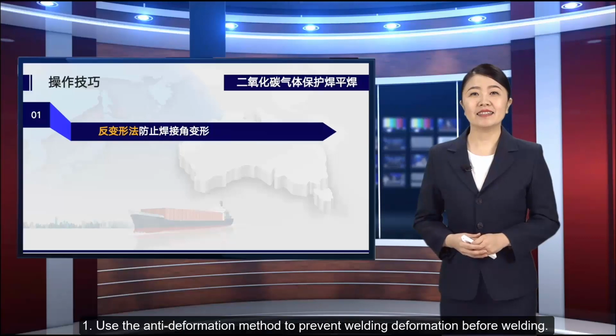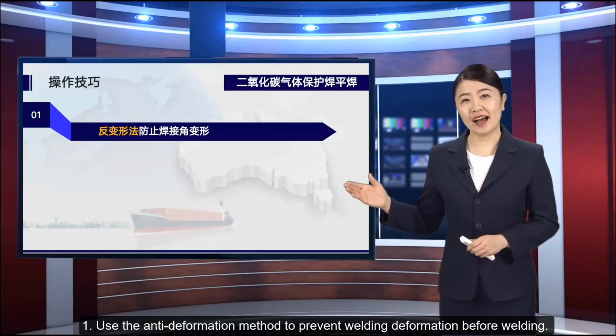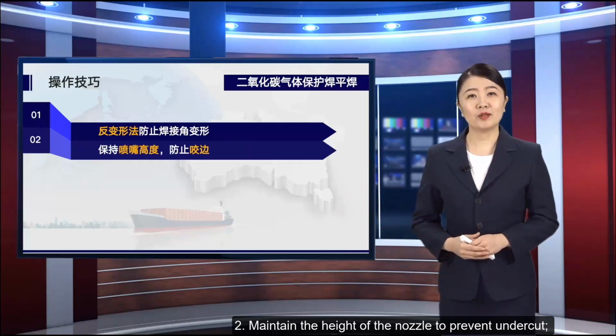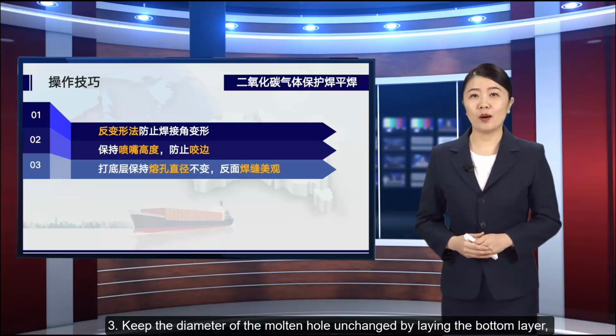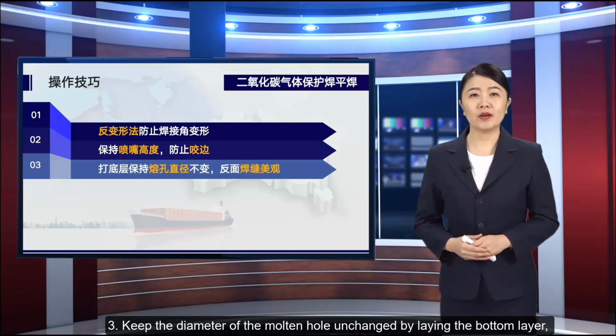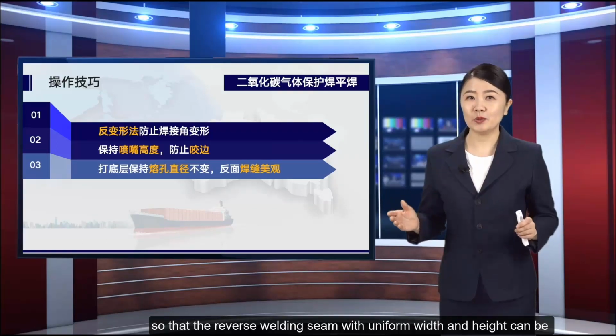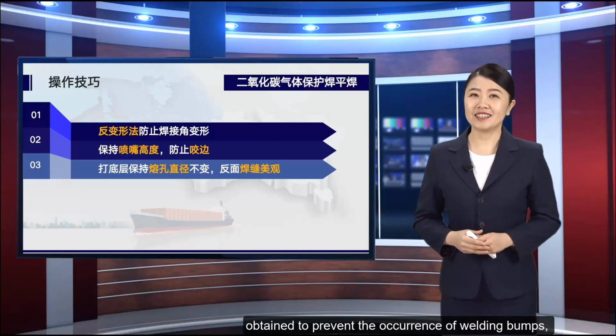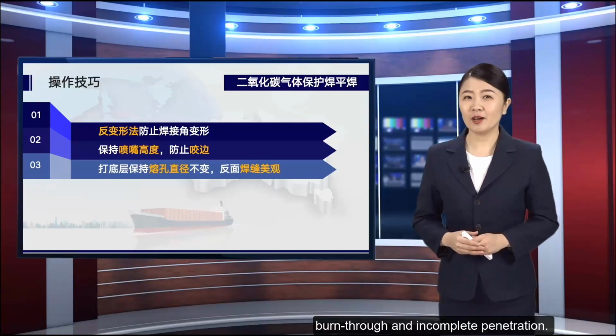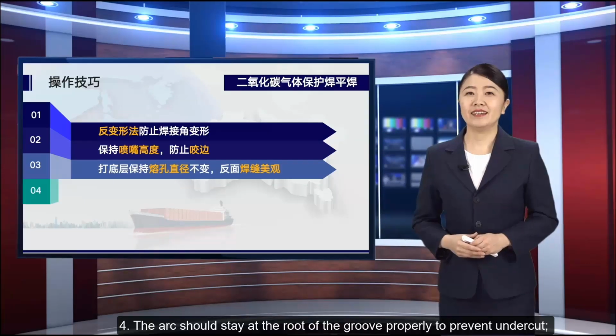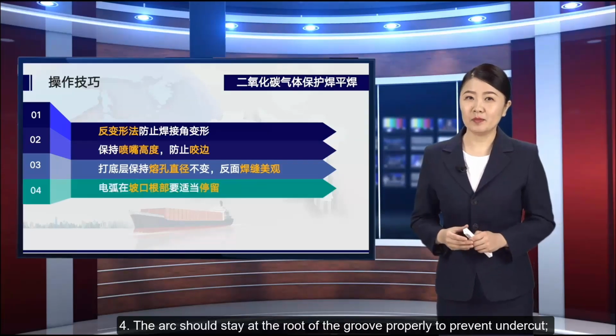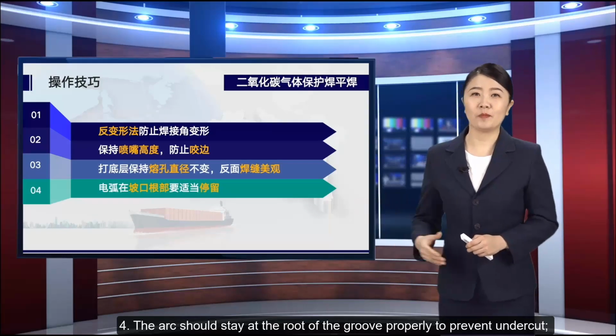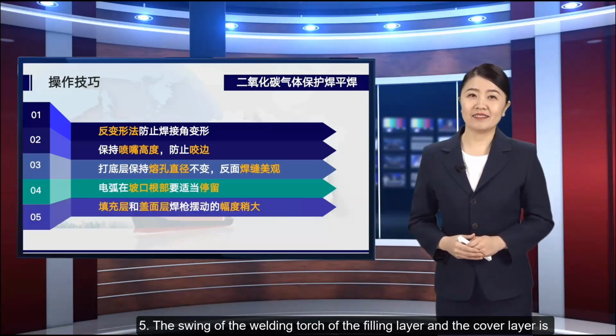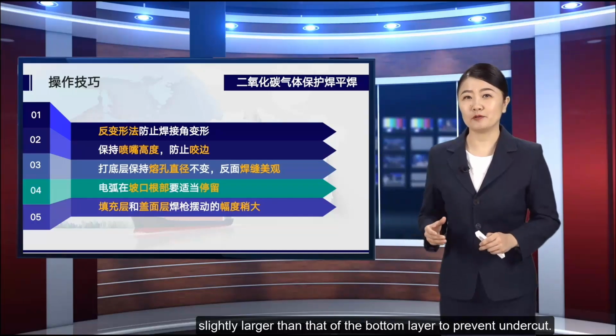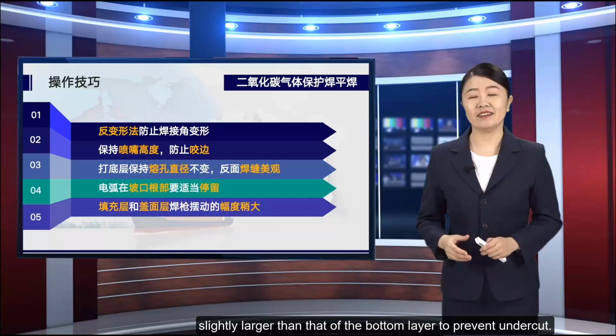1. Use the anti-deformation method to prevent welding deformation before welding. 2. Maintain the height of the nozzle to prevent undercut. 3. Keep the diameter of the molten hole unchanged by laying the bottom layer, so that the reverse welding seam with uniform width and height can be obtained to prevent the occurrence of welding bumps, burn through and incomplete penetration. 4. The arc should stay at the root of the groove properly to prevent undercut. 5. The swing of the welding torch of the filling layer in the cover layer is slightly larger than that of the bottom layer to prevent undercut.